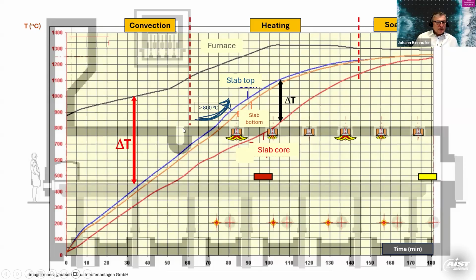What you also see here, as we said in the beginning, is no burners in the convection zone. We see very heavy heating in the heating zone. We increase the temperature of the furnace in the heating zone. We even go with a temperature higher than the final slab temperature in order to increase the delta T from the furnace to the surface temperature of the slab, in order to transfer as much heat as possible in that heating zone.